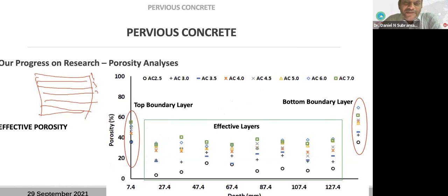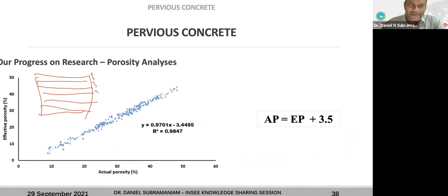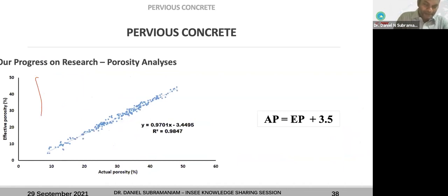So now this is the one I was talking about. But if you look at the middle layers, they're almost constant, but they vary with the aggregate to cement ratio, and also with compaction. But for a particular given sample, they are most probably constant. So this is something that we call the effective porosity, the application of effective porosity. Now this one gives us the relationship between actual porosity and effective porosity. You can see the uncertainty is much less. We have reduced it so much that we can depend more on it in developing the models.